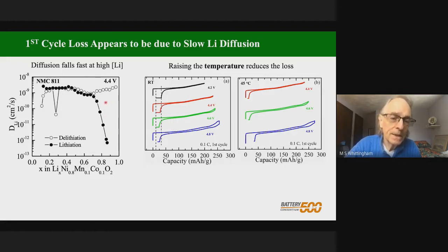And the actual mechanism here is a divacancy mechanism. So we need 2 vacancies in order for the lithium ion to jump. This is not an issue in taking the lithium ions out. So here the open circles are the diffusion for the lithium ions coming out until we get to the very last 5 or 10%. So this is very similar to a lecture hall. At the end of the class, you all leave without any problems.